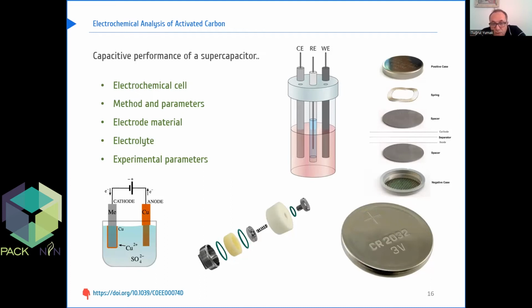A full electrode is a mixture of electrode active material, a binder, and a conductor. The specific capacitance decreases with increasing amount of binder because the binder blocks the pores. But the binder is needed, so the minimum amount of binder should be used for a perfect electrode.